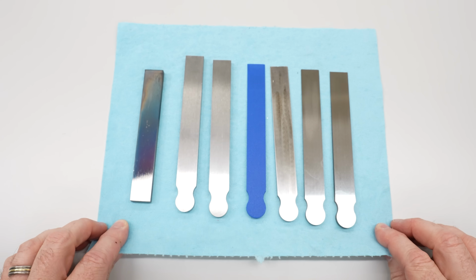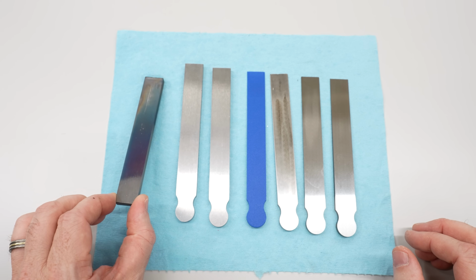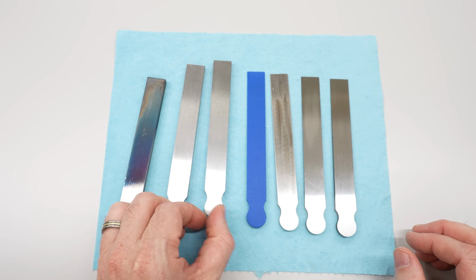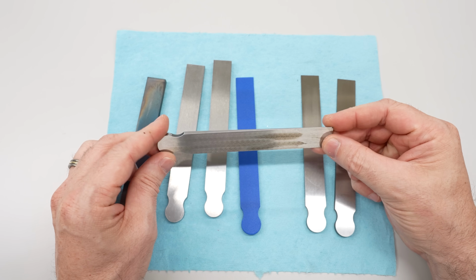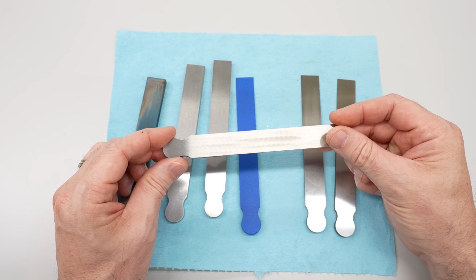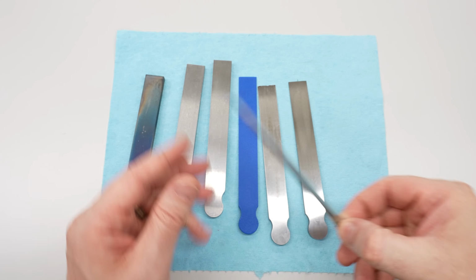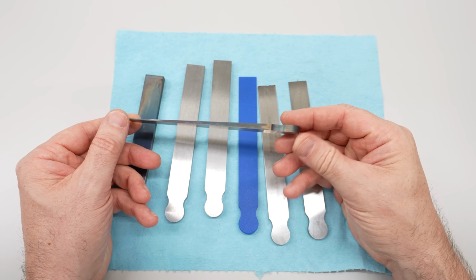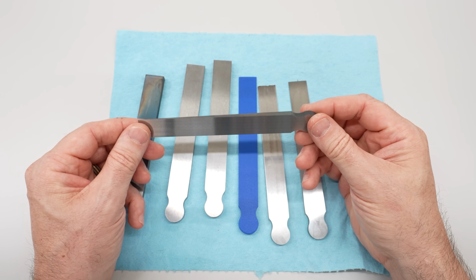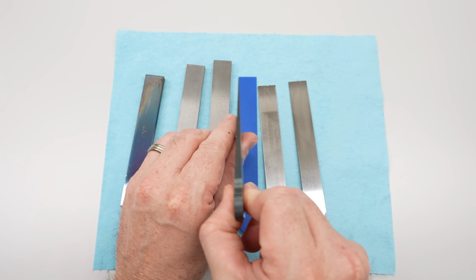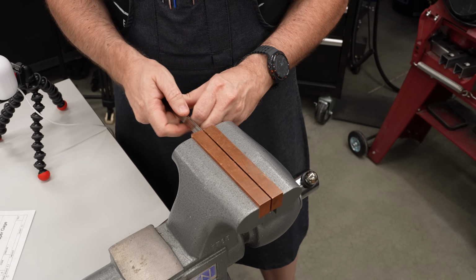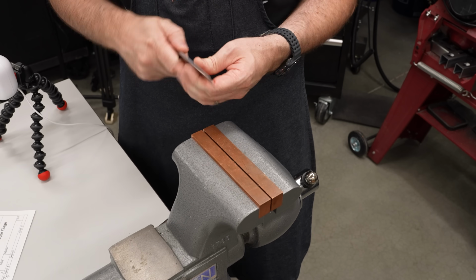For my first real grinding project on the machine and my first experience with A2 tool steel, I think it turned out okay. You can see that my setup part has some burn marks from overheating, but the other two that I ground more slowly turned out great. There's a little bit of residual warping in the parts, but it's easy to take that out by manually straightening in a copper jaw vise.